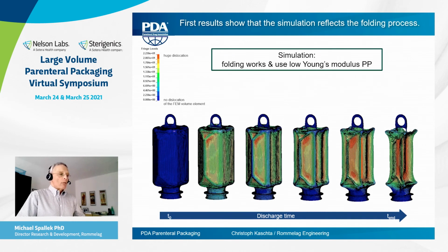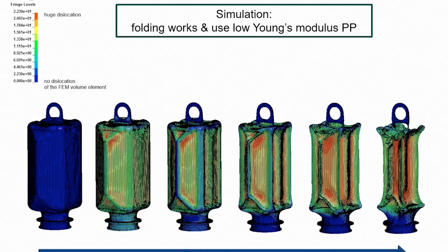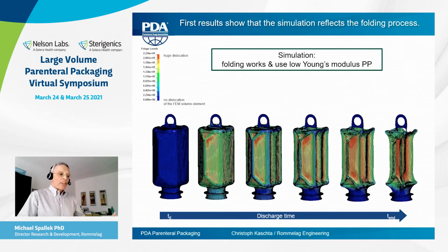The filled container is continuously emptied during administration. So this is discharge time, beginning and end. And at the end, you see a collapsed container. And from this simulation, we could learn about the detailed specifics of the container needed, as well as what has been foreseeable, that we want to use a material, a polypropylene preferably, with a low Young's modulus in order to make collapsing as easy as possible. We then built the mold and did the tests.